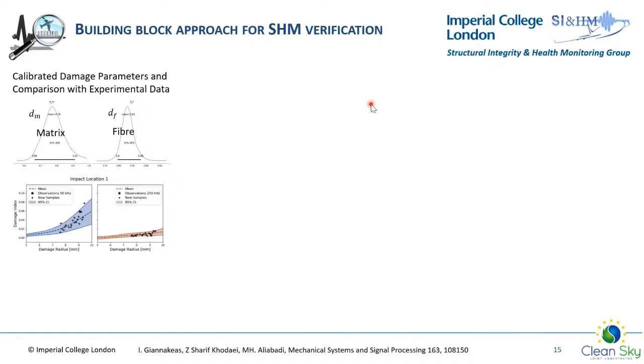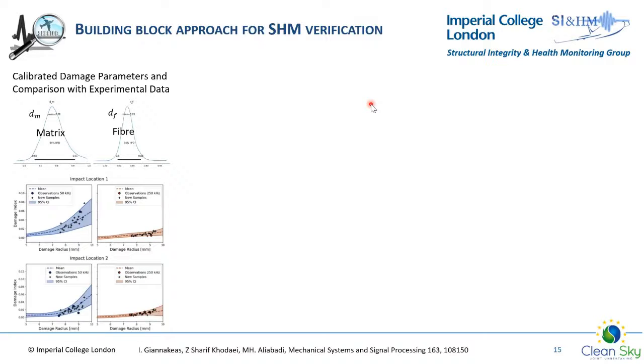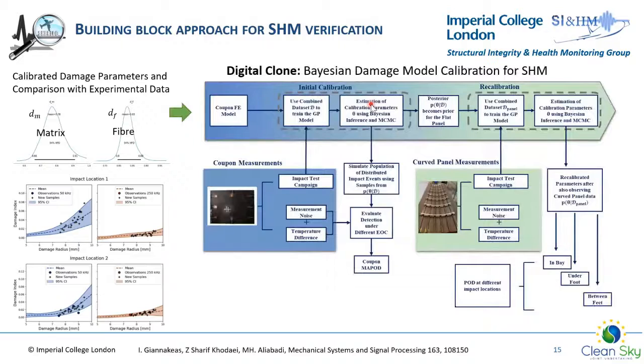So in this case, it is really a calibration of damage parameter based on experimental data, and it's using statistical analysis, so Bayesian updating. There's no time to really go through all aspects of it, but just to mention that the mechanical and experimental testing has to go combined or side by side with this numerical development, where we've developed a digital clone to have all these recalibrating parameters, and every time a new experiment becomes available, we update this to increase the